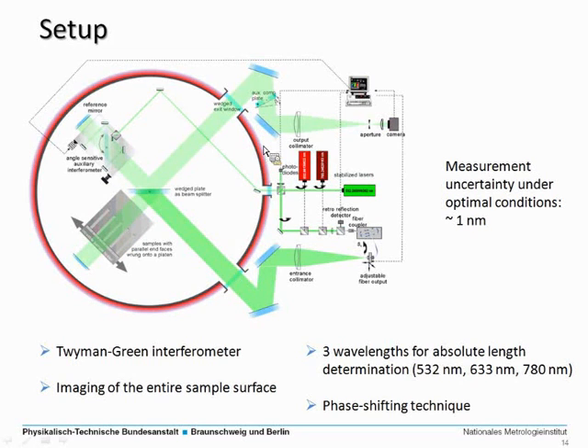The principle of this interferometer is a Twyman Green setup, and what we are doing, instead of just having a look at single points on the surface of the sample, is that we image the whole field of view of the sample. And then we apply this phase shifting technique, which I've explained earlier, in order to get the length from these measurements. The measurement uncertainty under optimal conditions with regard to temperature stability and